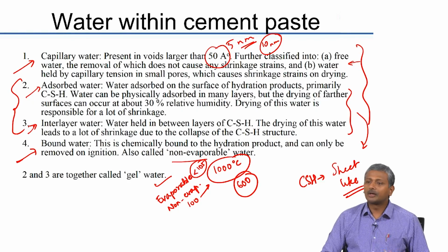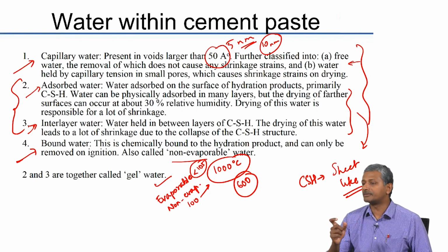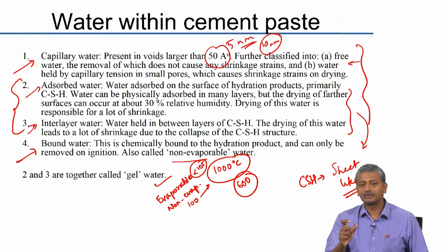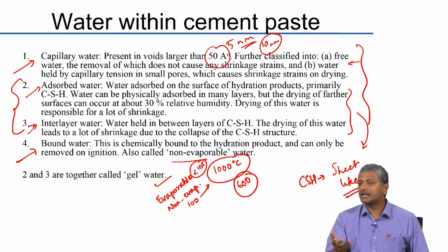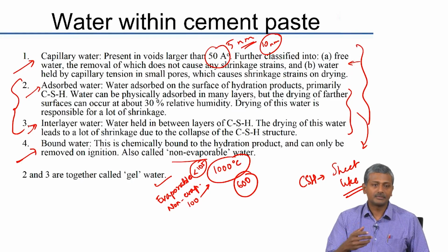Okay. Now primarily the reason why concrete is able to resist temperature is because all compounds in cement paste do not deteriorate until you reach temperatures of more than 500 degrees Celsius. Other compounds like ettringite or monosulphate, they may start disintegrating much earlier, like even 100 to 150 degrees Celsius.